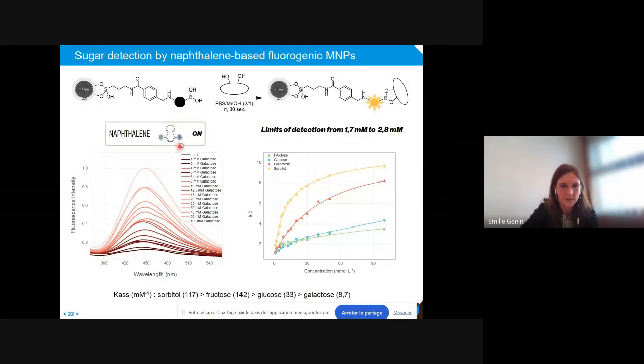For the other system, the off-on naphthalene system, we did the same. We once again observe the increase in intensity, and here you can see the different curves. We still have a significant increase in the fluorescence, interestingly quite similar to the solution.